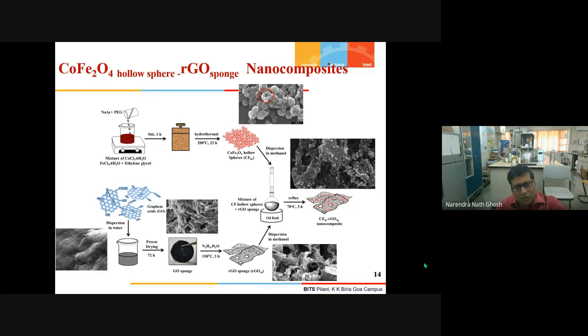Then we take this GO and treat it with freeze drying. And when we did that, we got a sponge-like structure which looks like this. Now, this GO still contains these functional groups. Therefore, by treating with hydrazine, which is a reducing agent, we reduce some of these functional groups and got the sponge-like structure of RGO. You can see it in this scanning electron microscope.